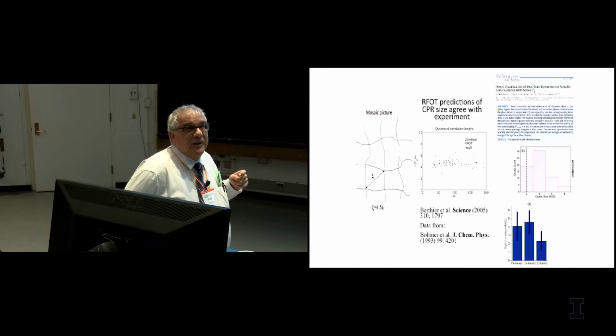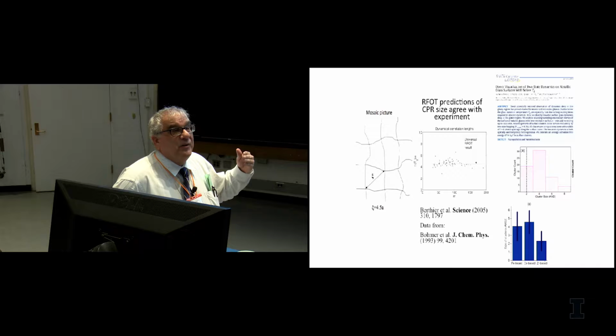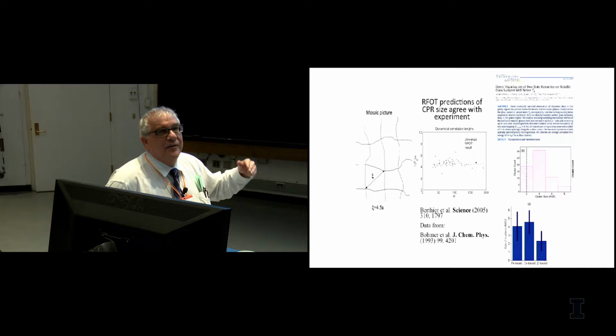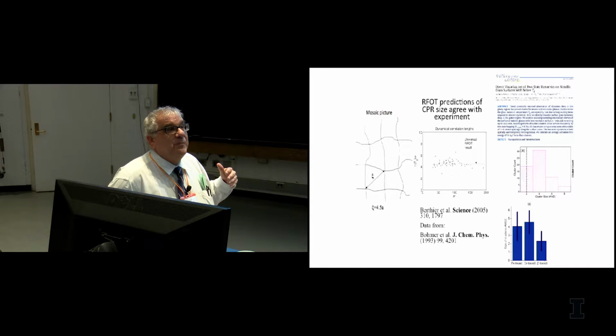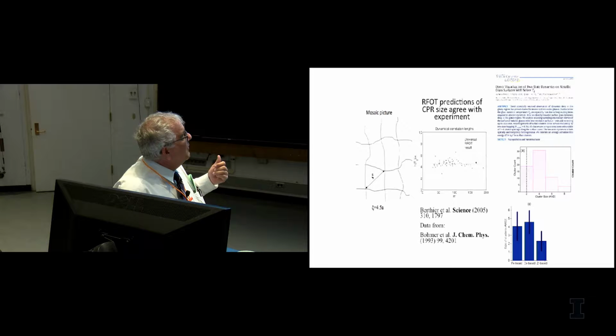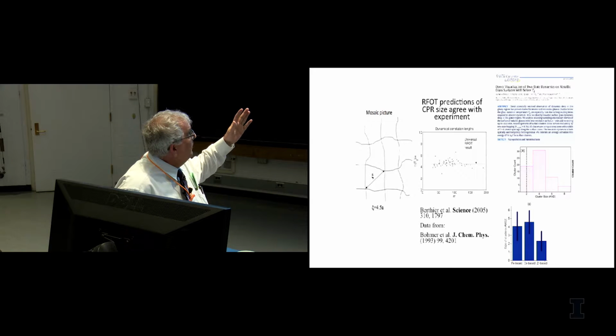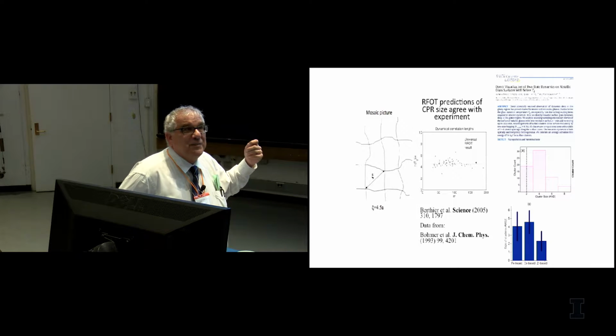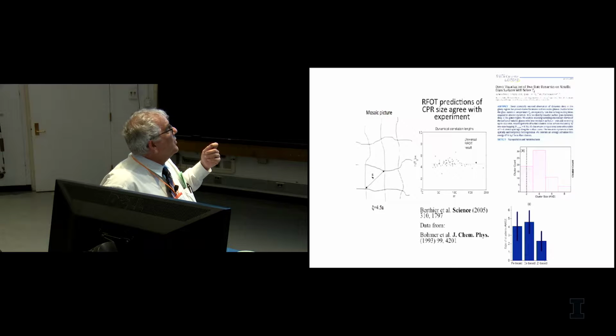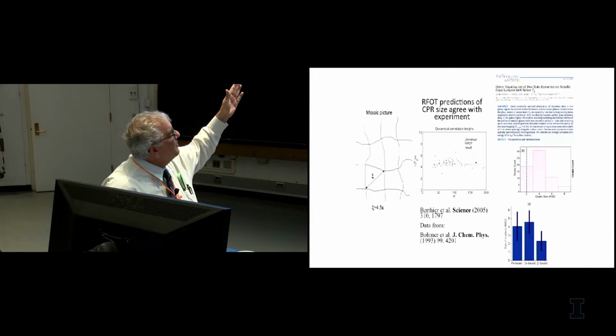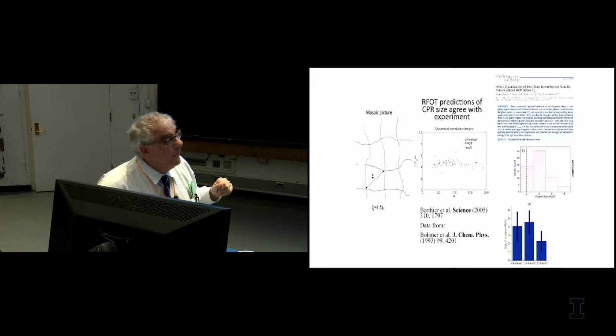How could we figure out something about that size? Well, indirectly we do, because every region doesn't have exactly the same energy. Instead, the energy fluctuates. And so there's actually a range of activation barriers when you look very carefully at the relaxation phenomenon in glasses. And the range of barriers can be predicted knowing this size. This has been turned into a very nice analysis that's actually slightly more rigorous by Giulio Biroli, Jean-Philippe Bouchaud, and Berthier in the early 2000s. And so you can back out from measurements of how non-exponential relaxations are a value of the correlation length. And this is done for about 50 substances by them. And you can see that the value is somewhere in the vicinity of 4.5 or something like that.